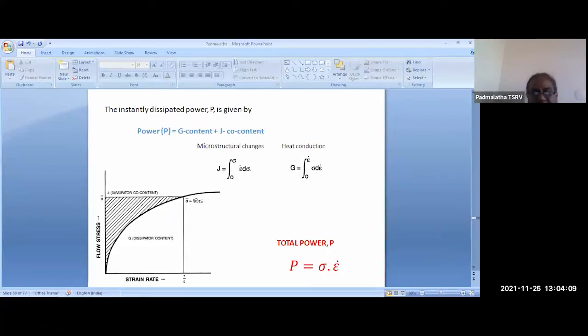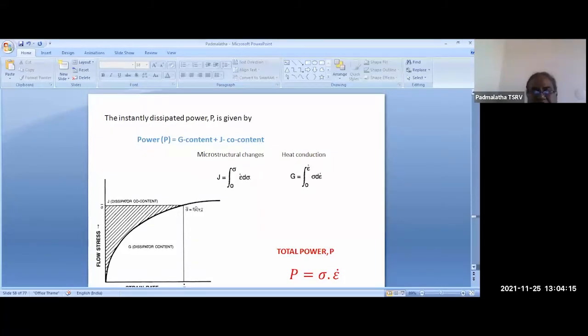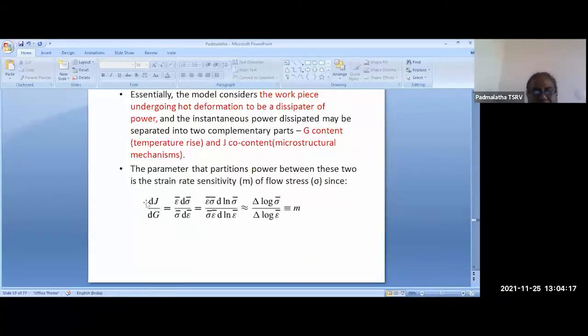So if we can relate these two, if we can find a fraction, how much is the J fraction with respect to the total power released? So if you see the ratio of dJ by dG, it is almost equal to the strain rate sensitivity. So strain rate sensitivity is a major parameter which will tell us about the hot working behavior of the material. It is a very important parameter for us, because the ratio of dJ and dG is approximately equal to m, that is the strain rate sensitivity.